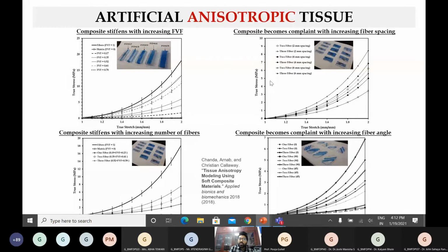The second is 2 to 3 different fibers. We have a limitation of really placing a lot of small collagen fibers here, which I'm going to show in a coming slide how we address. But here we could look at a limited number of fibers. So we went from 2 to 3 fibers to look at if there is any effect of fiber spacing, and second, the number of fibers on the composite property. We keep the same base material for the matrix and the fibers, but we keep changing the number of fibers, the fiber volume fraction. Here we do 1 fiber, 2 fiber, and 3 fiber. This is also being done. And the fourth part is we are looking at different fiber angles.